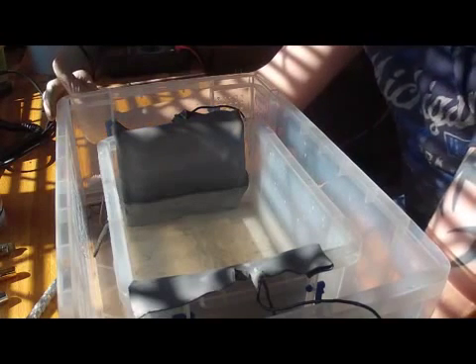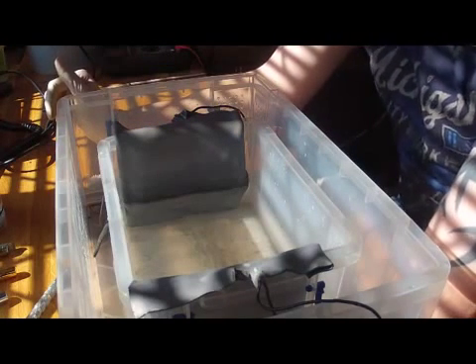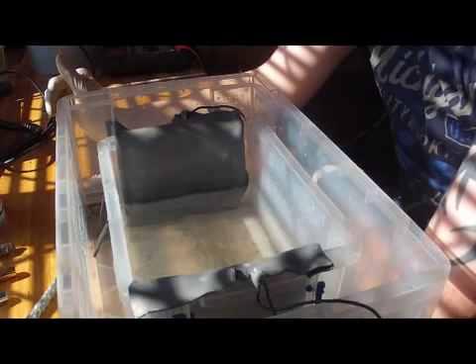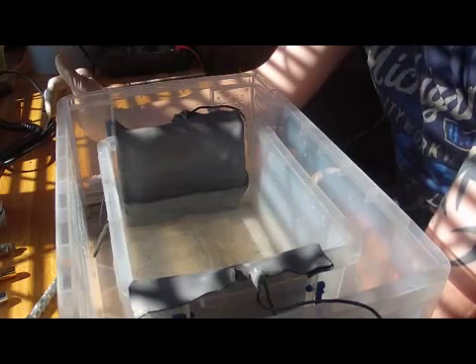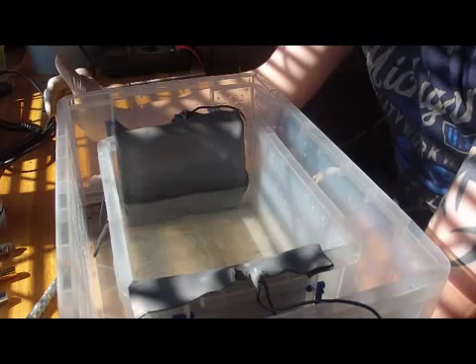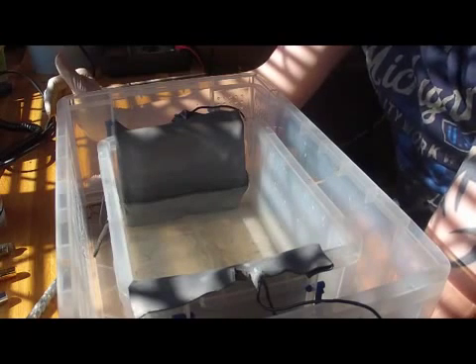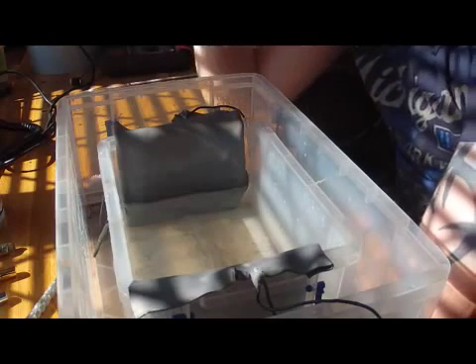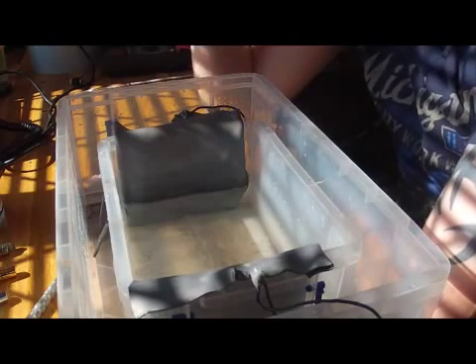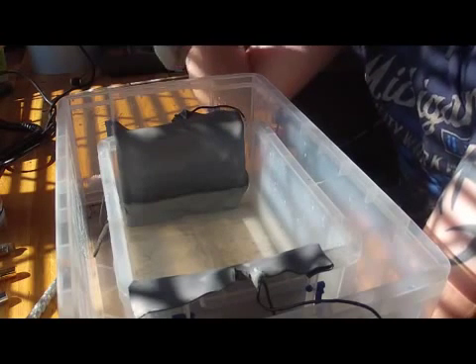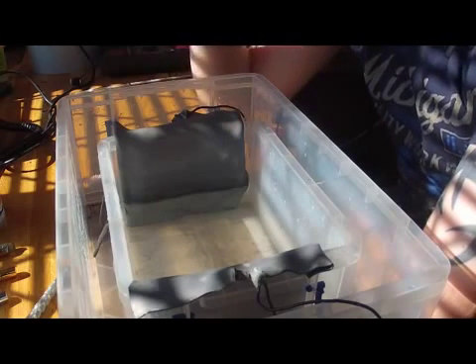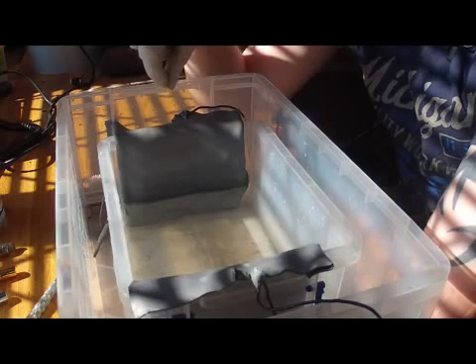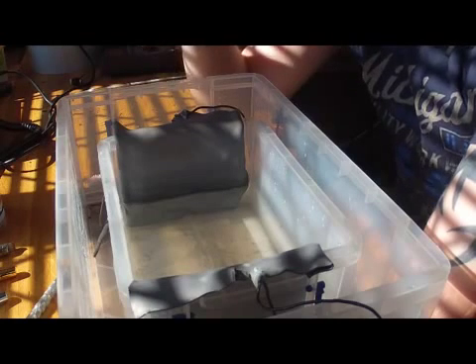Now the general rule of thumb with these cathodes. Mine's a bit overkill, but that's me for you. I do like to go bigger than I actually need. The surface area of your cathodes should be twice the size or more than the pieces you are anodizing. So for a little tank like this, this is perfect for doing pens. Obviously if I'm doing car parts, I'm going to need a bigger tank.